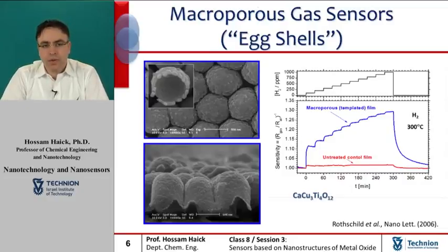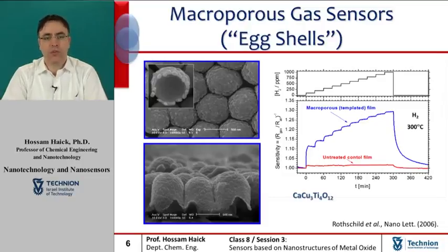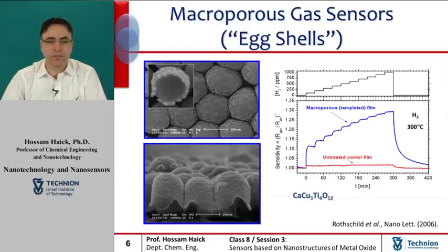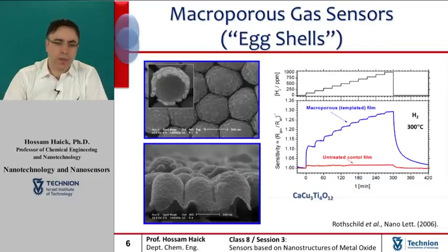In another example, chemical and physical synthesis routes are combined to prepare macroporous perovskite oxide thin films by pulsed laser deposition onto the PMMA microsphere templated substrates. The resultant films have a monolayer structure of quasi-ordered hollow hemispheres with high surface area, porosity, and permeability to gases.